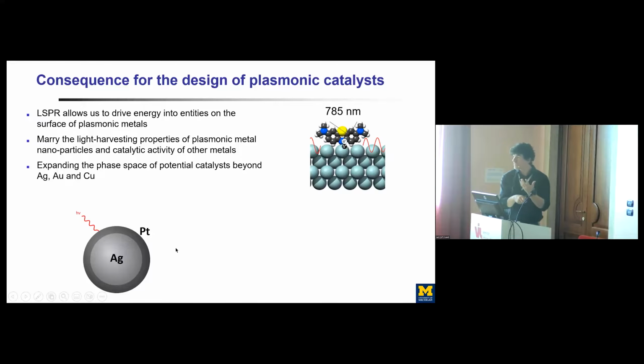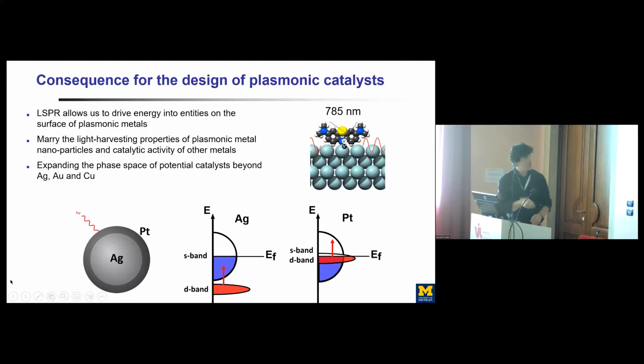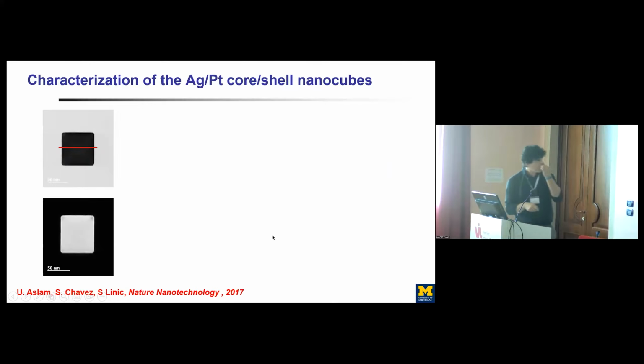So one model system that can be used to test that hypothesis is, for example, a silver nanoparticle that acts like an antenna covered with a very thin shell of, let's say, platinum. Now, platinum under UV visible light has these d to s transitions which are allowed in platinum. So you would expect the energy that's collected by silver to be preferentially dissipated through platinum through these d to s transitions. So we actually performed these experiments.